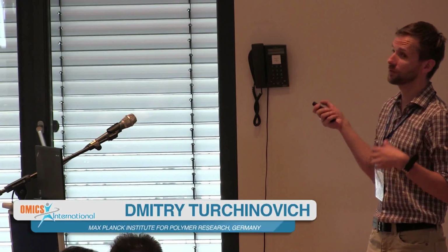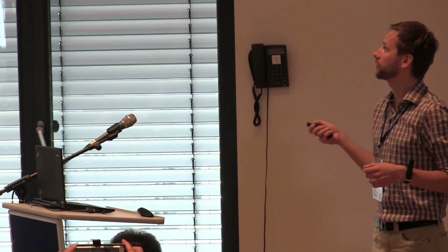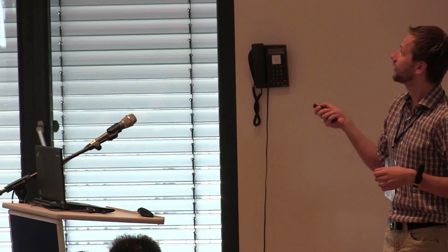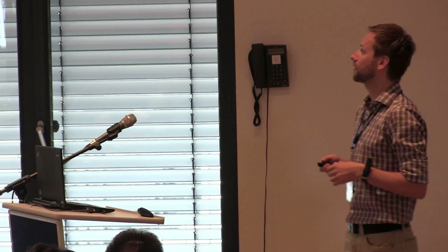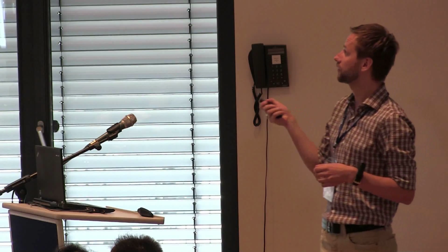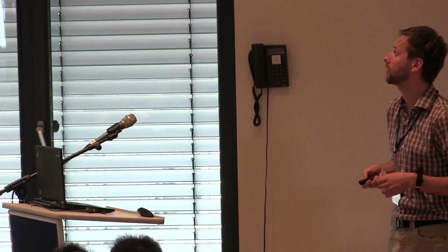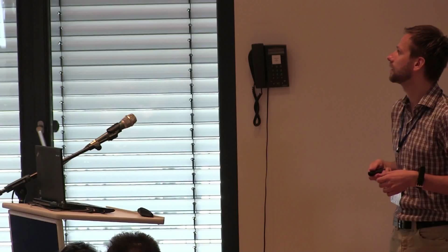What is color-coded here is different material systems. The red symbols are classical semiconductors like indium phosphide and gallium arsenide, and they operate at several hundreds of gigahertz, very close to 1 terahertz. The people who make those transistors that operate at about 1 terahertz publish them in IEEE journals or in APL. Those green symbols here represent the status quo for graphene transistors. This was taken from a review of 2 years back, and it's still the world record. The graphene transistors do not operate higher than about 400 or 500 gigahertz. And this is not because of bad engineering, as I will try to explain in the next slides.